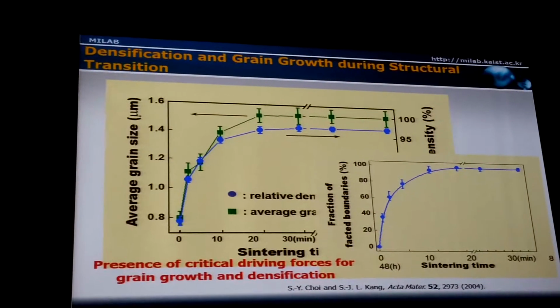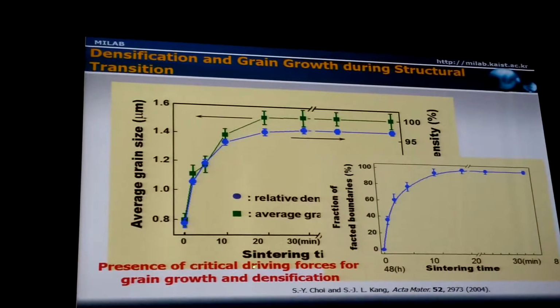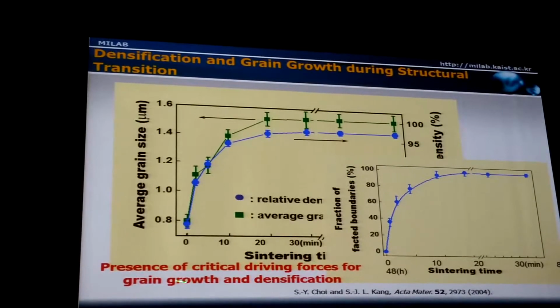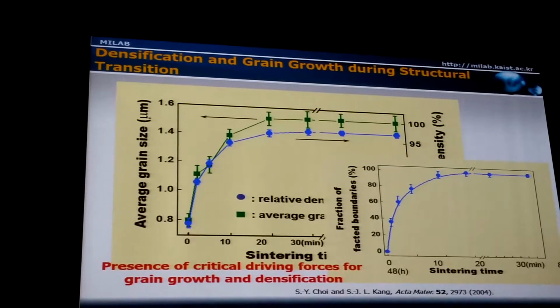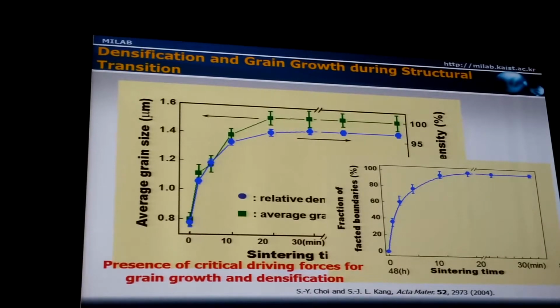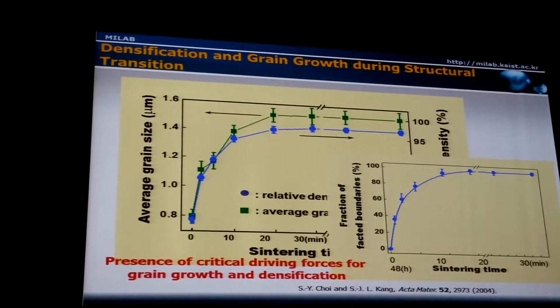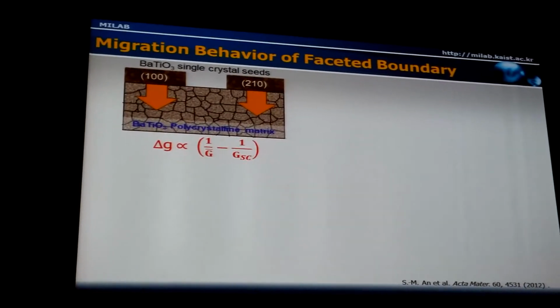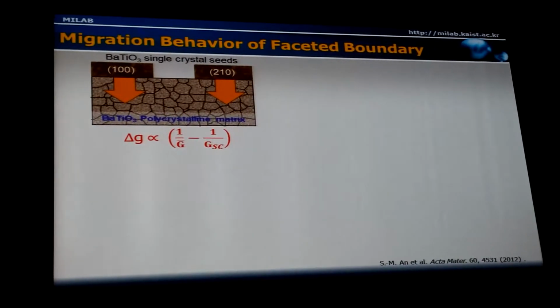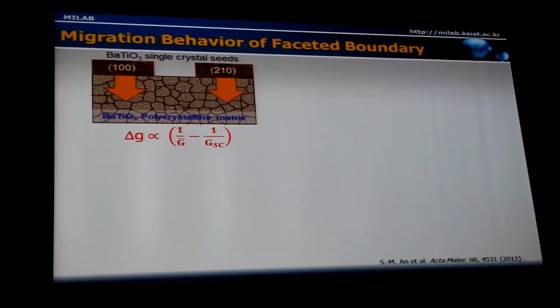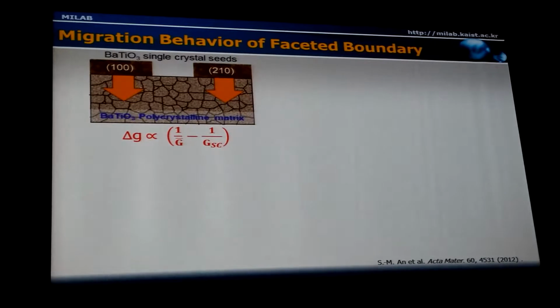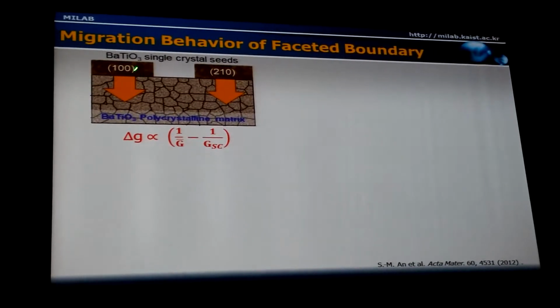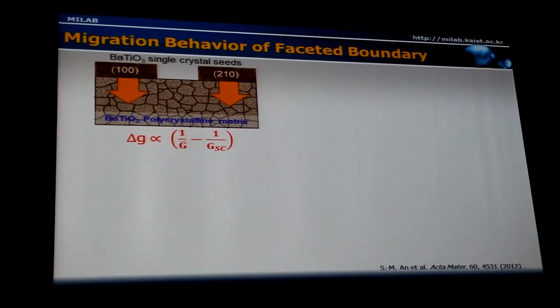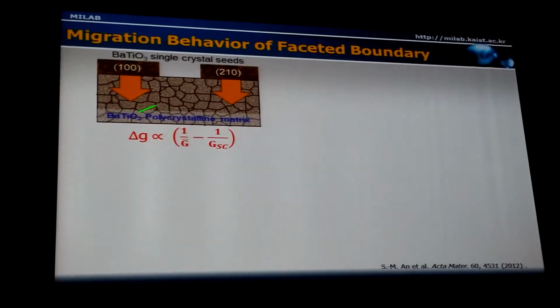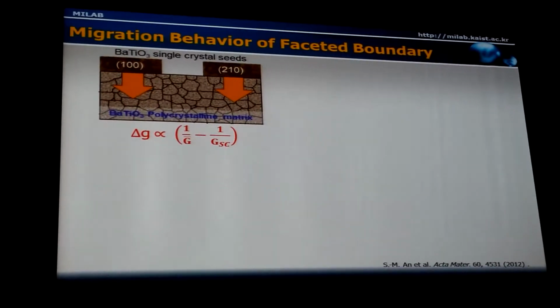This result indicates that there is a critical driving force for grain growth and densification when the grain boundary is faceted. There is no material transport. So we measured the kinetics of the migration of faceted boundaries by a model experiment using bilayer samples of single crystal and polycrystal: a 100 single crystal with polycrystal, and a 210 single crystal with polycrystal.